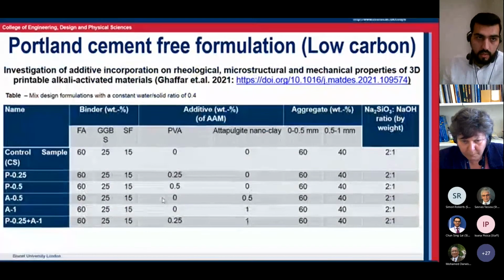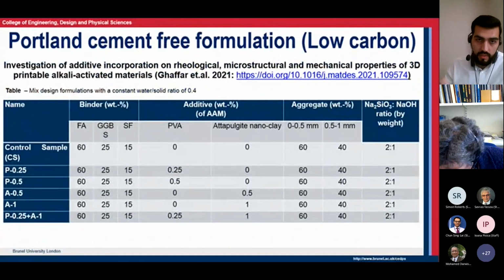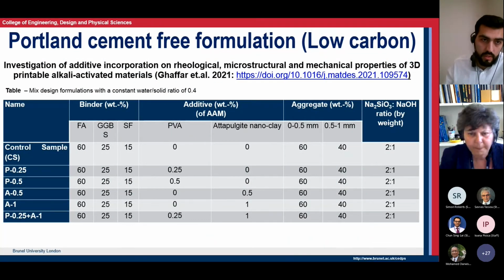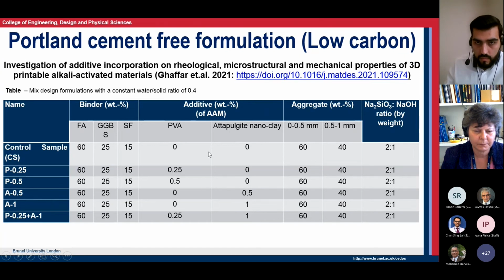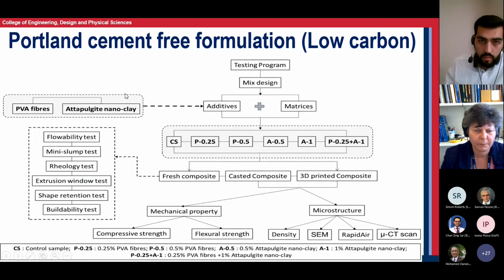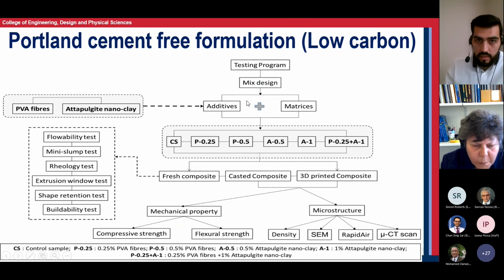So our studies, this is just one of the tables that I wanted to focus on. We've used these types of low carbon binders: fly ash, GGBS and silica fume. We use chemical agents to activate them, and we use some polyvinyl alcohol fibers and attapulgite nanoclay. These are the smart admixtures that I initially stated, and they are the admixtures that help us to get and optimize a certain performance. And here is our framework of the tests and the study that we conducted.